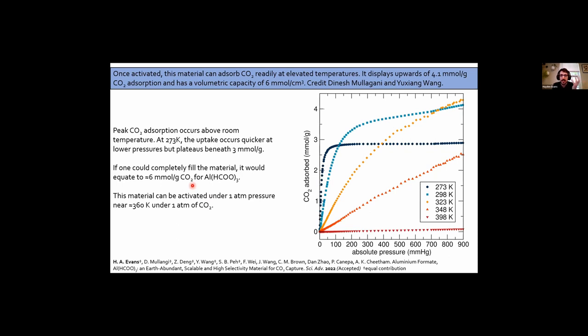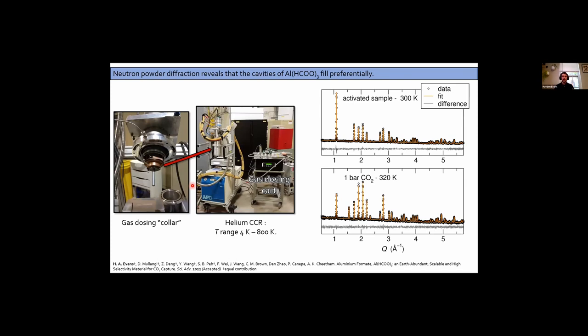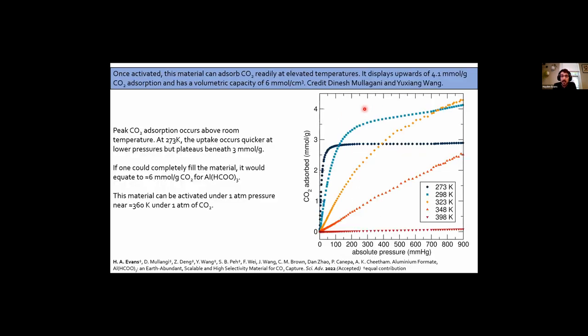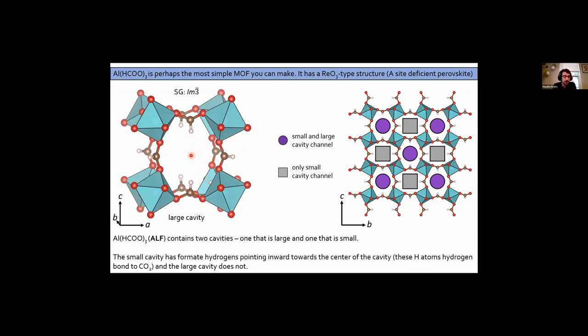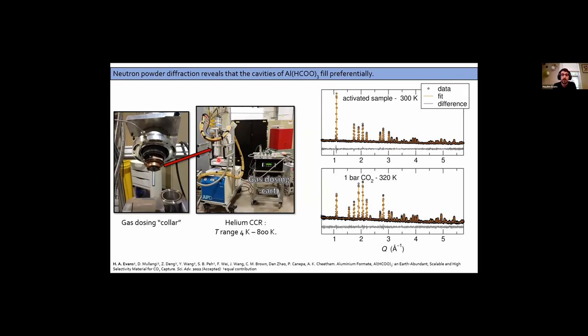So neutrons, how do we use them? I talked about how you can have the two flavors of gas dosing experiments. In this instance, we did a static pressure. So we held different pressures over aluminum formate, and we saw how the cavities filled. We could do this because we know how this filled. We know you're only going to get one CO2 based on size into this ultra microporous system. So here's that gas dosing collar that Craig talked about. Here's our vanadium can.